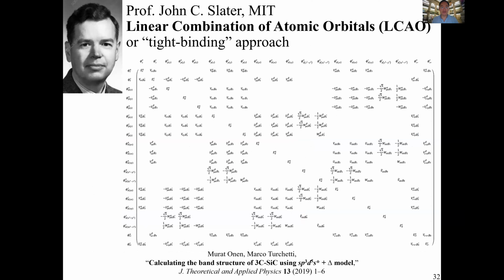And the motivation for this is really coming out of this tight binding approach. So in the linear combination of atomic orbitals, you construct this electronic Hamiltonian, where these are the matrix elements. So for example, this is trying to represent the band structure of silicon carbide using 1 s orbital, 3 p orbitals, 5 d orbitals, and an excited s orbital. And you construct this 20 by 20 Hamiltonian matrix, where let's say this submatrix, when you rotate your head, you're going to redefine your d orbitals, and then this matrix would rotate according to the tensor transformation laws.